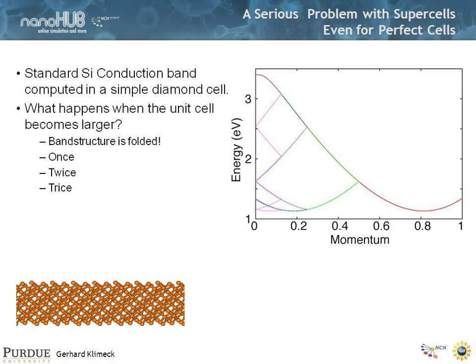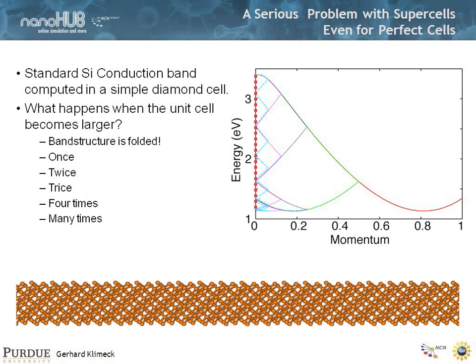You know where this is going. At the end we might have a very big cell where k — the original translational k we used as a description of a single cell — is no longer evident. All we get is a set of eigenstates sitting on this axis, and for numerical purposes we may not even be guaranteed to catch all of them. Somehow we have to find a way to unfold this — unless we're just interested in finding the bottom of the conduction band, which is fine. But sometimes you want the effective mass, which means you need a couple of states to get the derivative.